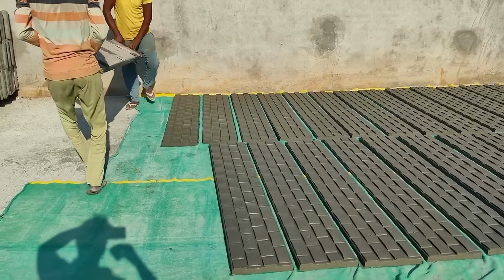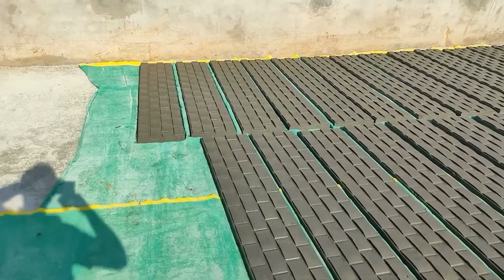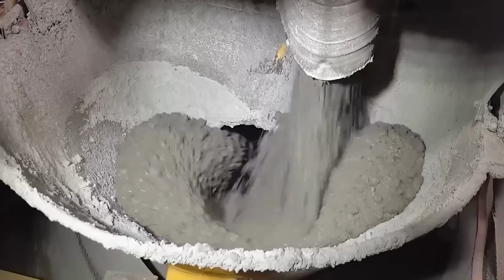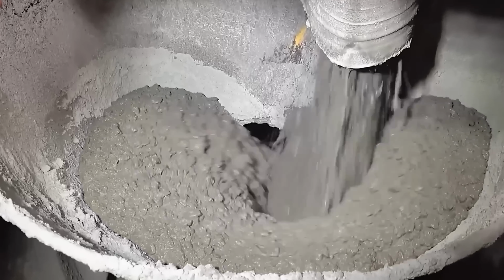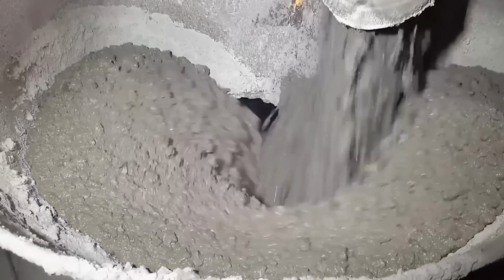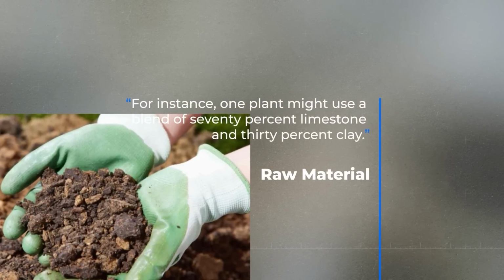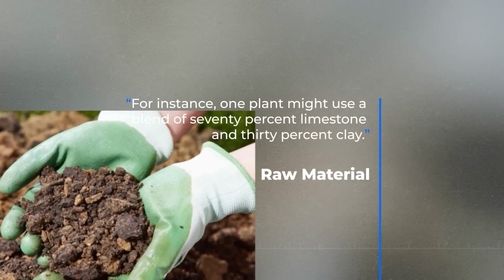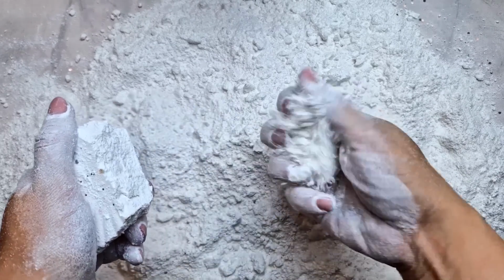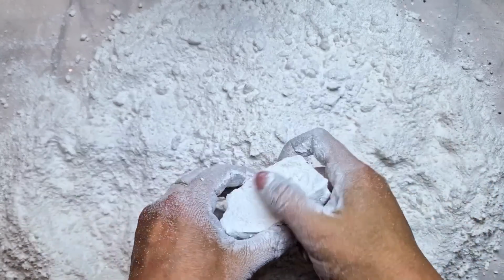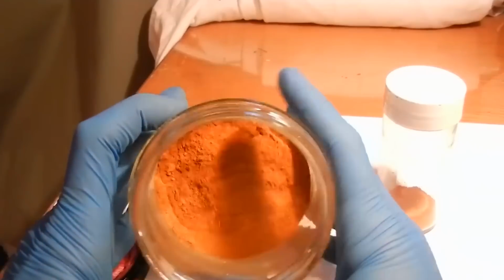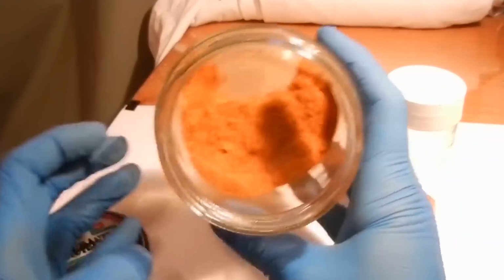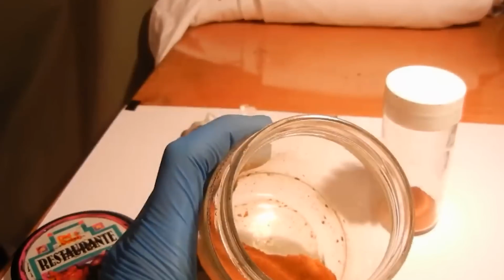No two cement plants have the exact same raw mix design. This variability stems from the diverse compositions of raw materials available. For instance, one plant might use a blend of 70% limestone and 30% clay, while another might mix 95% chalk with 4.5% silica and 0.5% iron oxide to achieve the desired chemical composition in the raw mix.